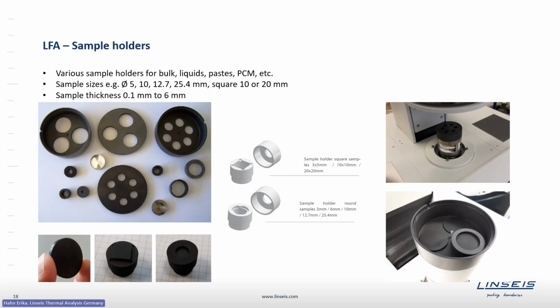Coming now to the different sample holders. The basic idea of the laser flash is to measure solid materials with thicknesses ranging from 0.1 to 6 millimeters, depending a little on the kind of material. Our sample holders allow various sample sizes, typically from 10 millimeter diameter to half an inch or 1 inch diameter. There are also some sample holders for square samples of 10 or 20 millimeters. But all of these sample holders are designed the same.